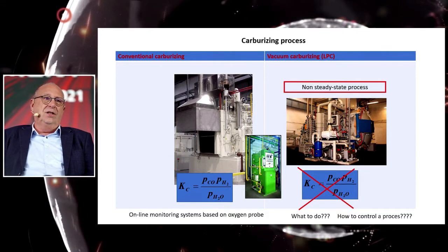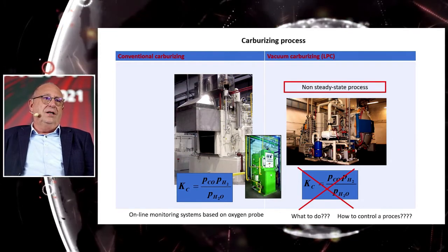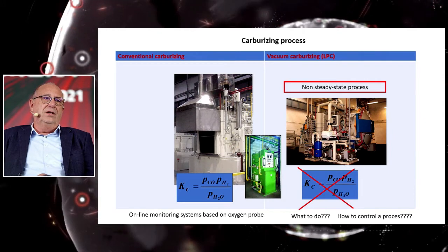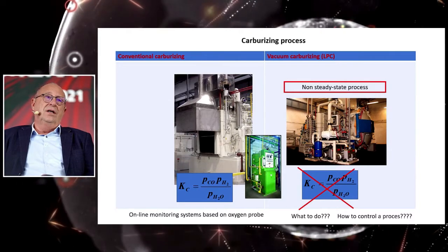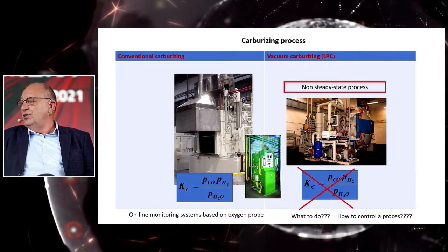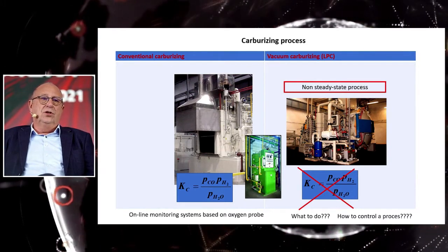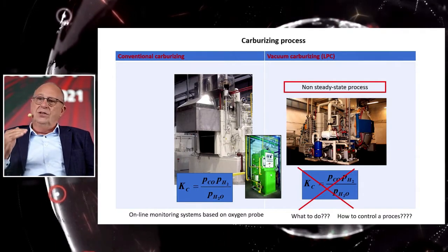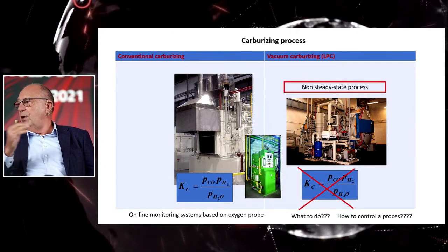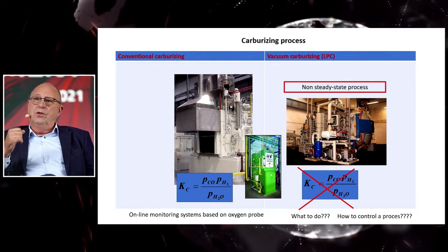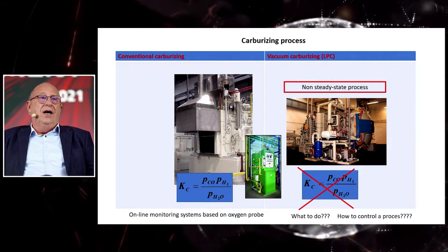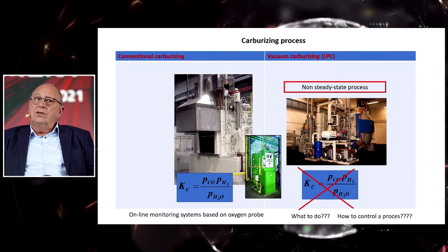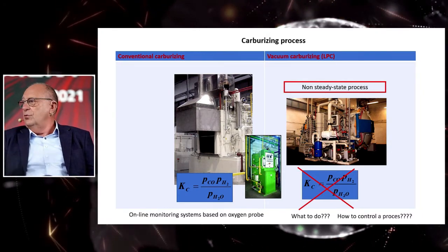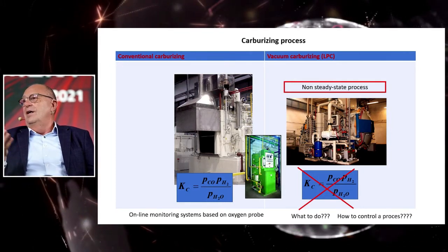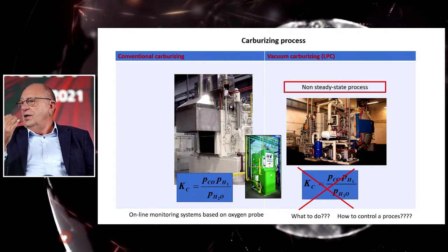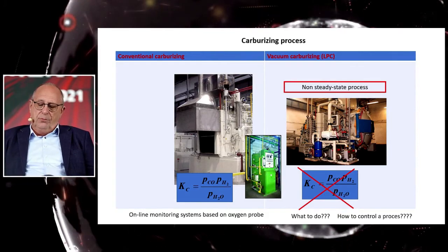So what is the basic difference between traditional gas carburizing and vacuum carburizing? Traditional gas carburizing is controlled by the carbon potential value. The carburizing gases are supplied from gas generators, and online monitoring systems based on an oxygen probe keep the potential at the required level. This is the critical factor for solving the diffusion equations, so we are able to practically control the development of the carbon profile online. Vacuum or low pressure carburizing is generally a non-steady state process, so it's hard to keep and control the equilibrium. The question is what to do. Absolutely, artificial intelligence tools are necessary to foresee and plan the schedule of each vacuum carburizing process.